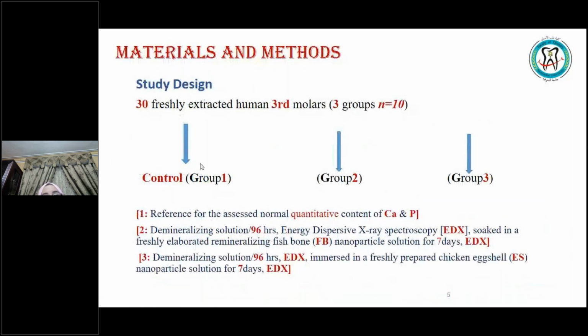Designing the study, 30 of the 34 freshly extracted teeth were divided into 3 equal groups, where each group is formed of 10. Group 1 was considered the reference for the assessed normal quantitative content of calcium and phosphorus. The second group was demineralized first for 96 hours. Then it was investigated with energy dispersive X-ray spectroscopy.